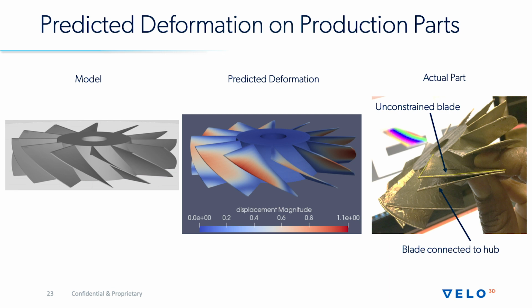And we've got two cases, one where the blades are connected to the hub as was simulated, and then the other case where the blade was printed just by itself, so it didn't have this large mass tugging on it. And you can see in this case that the unconstrained blade relative to the one that's connected to the hub, you can see this very large difference in shape and deformation that occurred, validating the simulation.